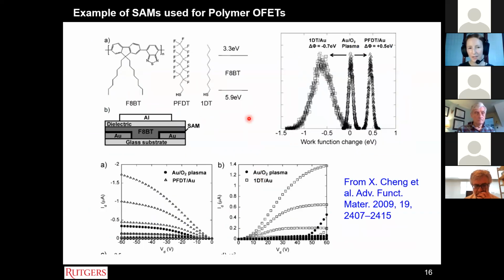This is just an example I pulled from the literature on the use of SAMs in polymer field effect transistors. The idea has been around for quite a while, but for OFETs, you would add SAMs to the gold back electrode and then spin coat the polymer on top, and the SAM will improve the charge injection into the F8BT. They looked at a few different self-assembled monolayers, again with just one sulfur attachment, PFDT and 1-decanethiol. And they showed that depending on the self-assembled monolayer, you can either get an increase or a decrease in the surface work function of the gold in this case when they use those SAMs.